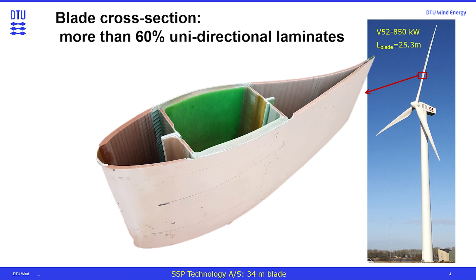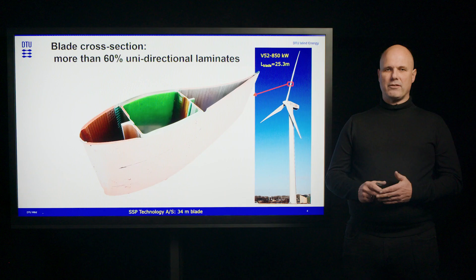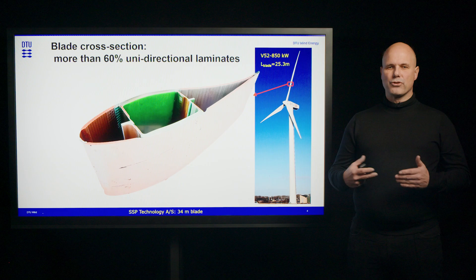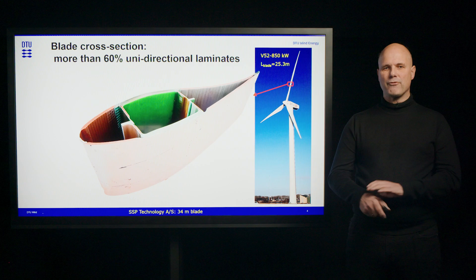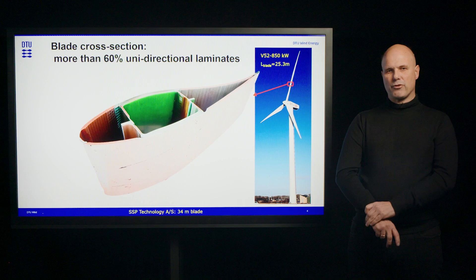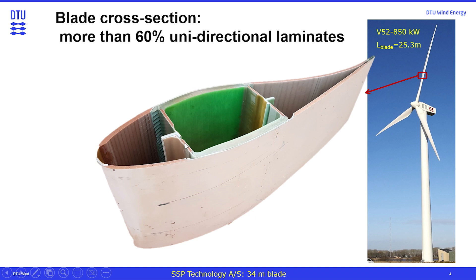We will look into the turbine blade. Everything starts with the blades, and one of the major tasks when increasing turbine size is to increase the length of the turbine blades. For that, we need a good understanding of what requirements we have for the material. In the DTU Wind and Energy Systems group, we are more than 40 people working just with composites for wind turbine blades. If we look at a cross section, then more than 60% of the composite used is actually unidirectional laminates, mainly located in the spar cap region, taking up the load for the flatwise loading of the turbine blade.